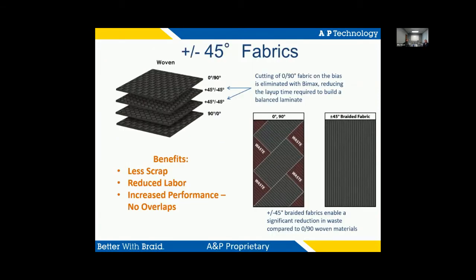I mentioned a few slides before that braid naturally forms at ± 45. We pass that efficiency onto the customer in the form of our Bimax or TX45 fabrics. So if you are cutting on the bias, in this case, 0/90 on a ± 45, and then kitting and laying it up, I think you'd be better served using your 0/90 and then feathering in ± 45. Or obviously if the design calls for 45 across the board, as in the case with a lot of high aspect ratio parts or something that's torsional design, just go straight to the source, and then off the roll you can have a ± 45 solution, saving upwards of 30% scrap and a significant amount of layup time and management.